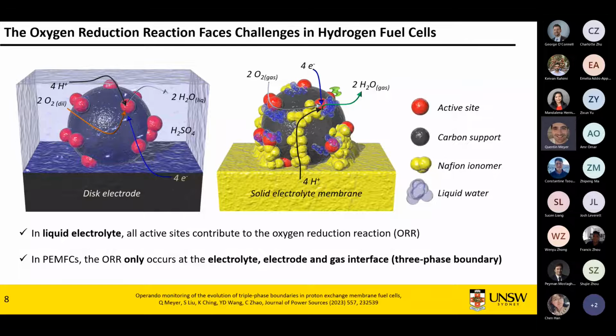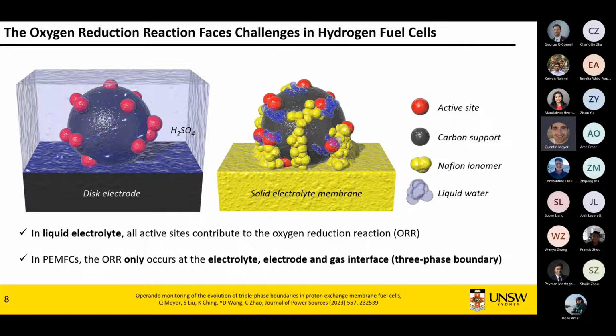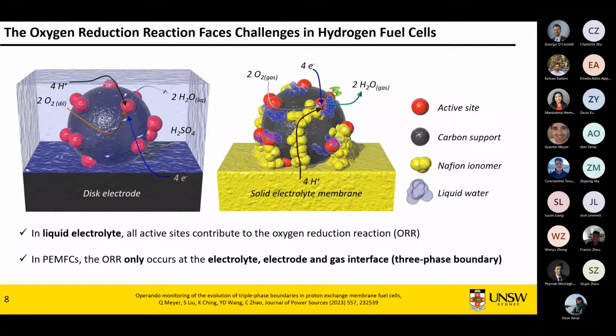Then you move to a real device. In a real device, you typically have an ionomer, which is Nafion, that binds the materials of your ink together. Then you coat it on a membrane, not on an electrode, and you start having all sorts of problems. The challenges that become significant can be proton transport and gas diffusion. You want to produce water, but if you produce way too much water, you have flooding. Flooding is not a good thing.